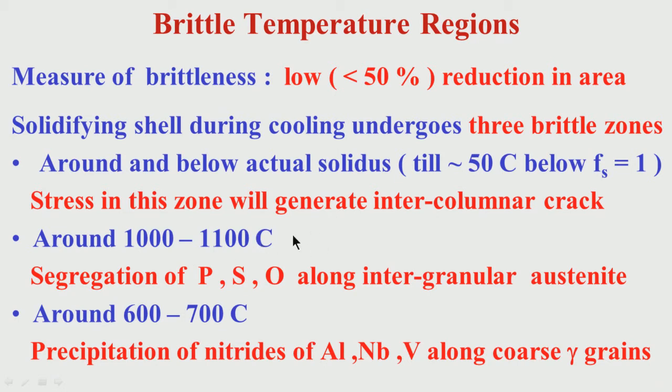Whatever delta ferrite grains were there have transformed to austenite either during solidification, or for very low carbon chemistries or very low nickel equivalent by chromium equivalent stainless grades, they transform at lower temperatures during cooling.